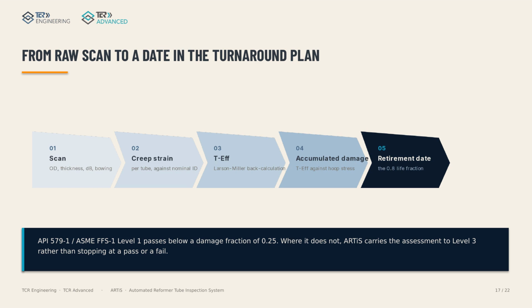Under API 579-1 and ASME FFS-1, a damage fraction below 0.25 passes at level 1. Where it does not, ARTiS carries the assessment to level 3. Retirement is set at a life fraction of 0.8 because beyond that, the damage rate turns exponential.